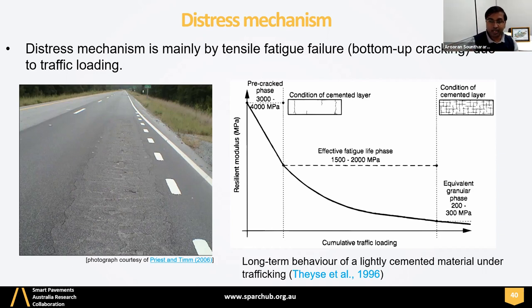So what happens to the modulus over the course of pavement life? With cumulative traffic loading, as the number of loads increases, the resilient modulus drops with cycles. When I say resilient modulus, remember this type of pavement bends. Therefore, they take into account the flexural modulus or bending modulus in the pavement.